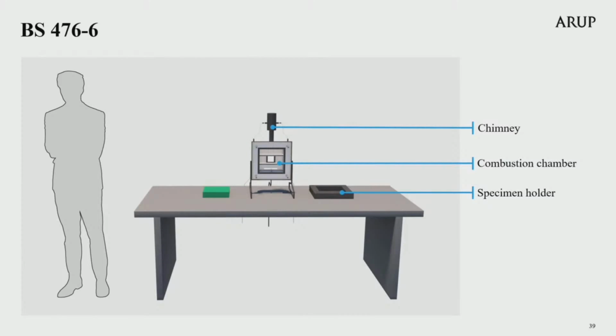The test apparatus comprises a combustion chamber with a specimen holder that is fixed onto the front face. The combustion chamber contains a horizontal gas burner tube and 2 electrical heating elements, and is surmounted by a removable steel chimney and cowl. The specimen holder is made from calcium silicate board, having the same dry density and properties as that of the walls of the combustion chamber. The holder is recessed to take a specimen of area 225 mm by 225 mm, with a recessed depth of 12.5, 25 or 50 millimetres, depending on the specimen to be tested. A non-combustible compressible gasket 1 millimetre thick is provided for interposing between the specimen holder and the combustion chamber to assist in obtaining an adequate seal.